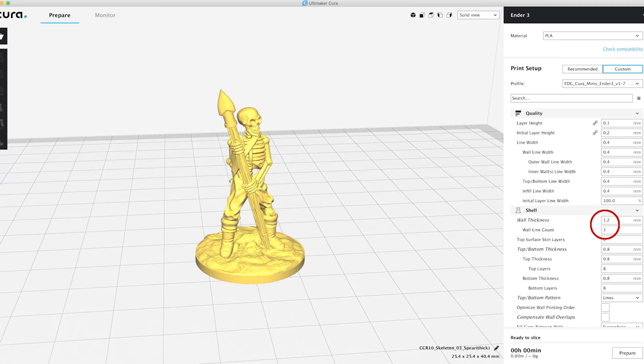Wall thickness, now this is where a lot of people disagree with me. They think you can get by with just two walls, or it would be 0.8 millimeter wall thickness. And I don't like this. If you're printing with 100% infill, yeah, that's great. For me, I prefer printing with less infill, as discussed earlier, and thicker shells. And it gives me all the strength I'm going to get, regardless of what the infill is, for thinner areas, in this case, the spear and the ankles. And the neck of the skeleton.